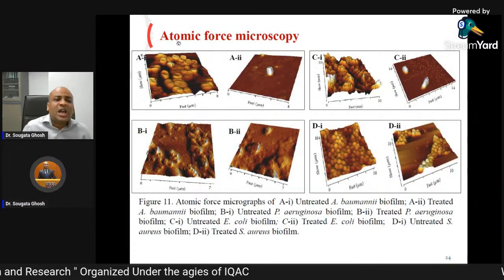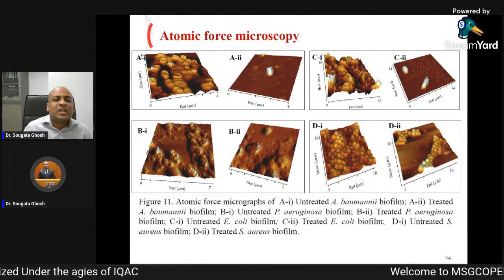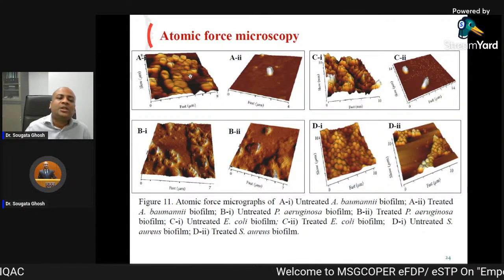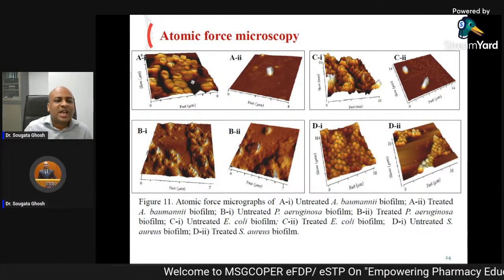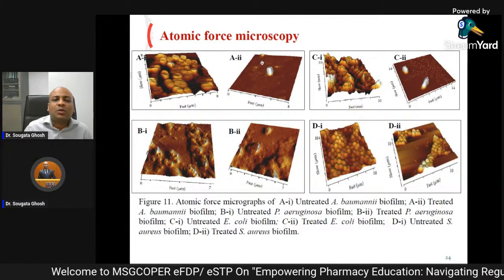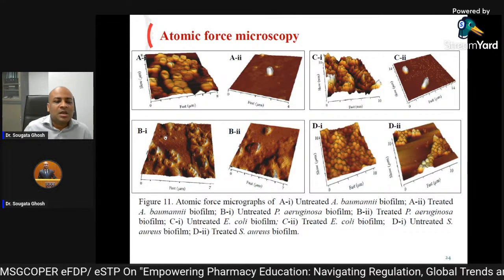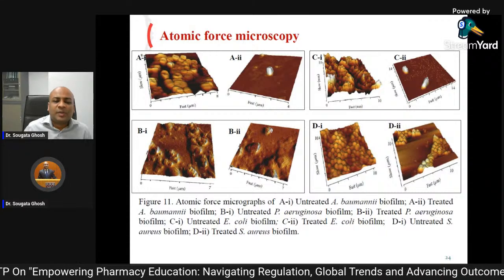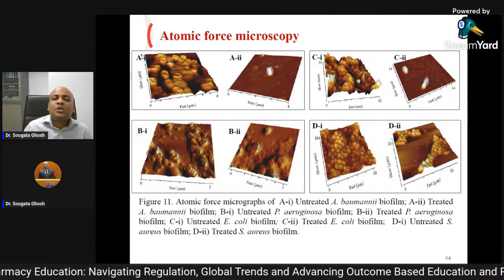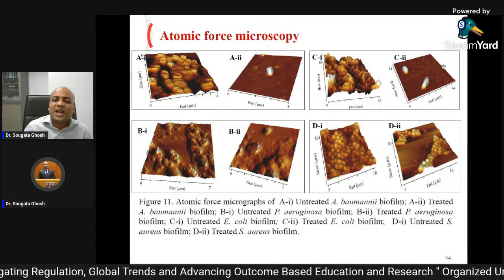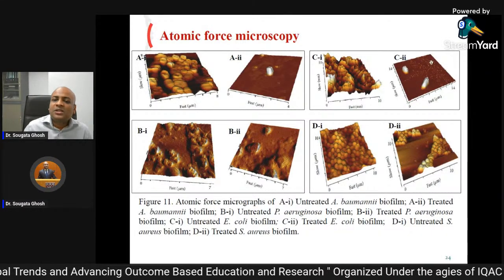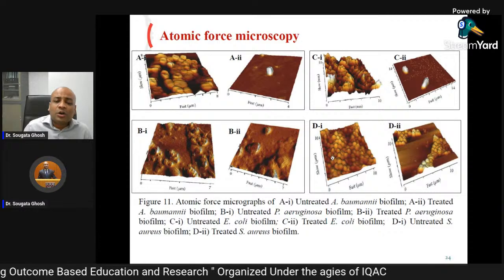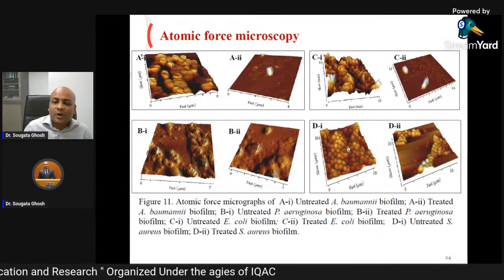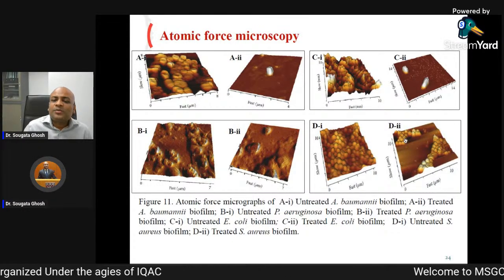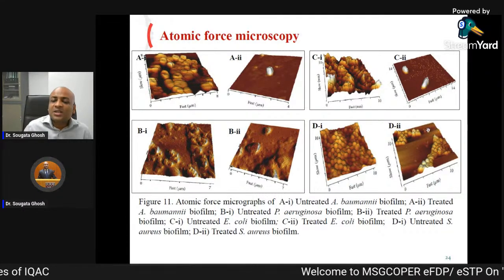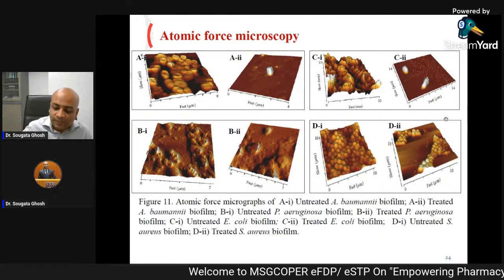We wanted to confirm with the help of atomic force microscopy, and in atomic force microscopy also, we get 3-dimensional images. You can see Acinetobacter baumannii. After treatment, only 1 cell was left. Pseudomonas: this entire plate was covered with Pseudomonas biofilm. Only a few cells are left. E. coli: only 2 cells are left. You can see the nanoparticles, the nanocrystals on the substrate. Staphylococcus aureus: only patches of staphylococcal biofilms are left. You can see this substrate is exposed after treatment.